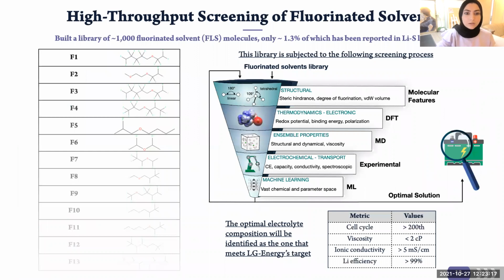Now I'm going back a little bit to the lithium-sulfur project, in which we relied on the MISPR infrastructure for all the computational work that we did for this project. And as I said before, the type of the co-solvent used in the lithium-sulfur electrolyte determines the solubility of the polysulfides and therefore the electrochemical performance of the battery.